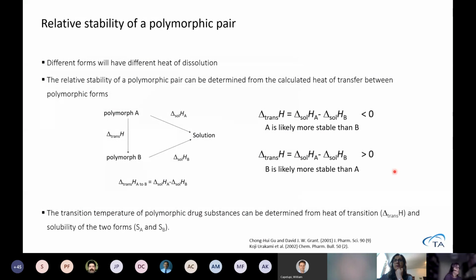So just start with the relative stability of a polymorphic pair. Different forms would have different heat of dissolution. So we can determine the relative stability of a polymorphic pair by calculating the heat of transfer between the different polymorphic forms. Well, you can do this with a DSC. You can get the transformation by increasing the temperature and get the transformation from one polymorph to another. We can also do it by dissolution calorimetry. As I say, we put it in an ampule, and we crush the ampule in a bulk liquid, and we measure the heat of dissolution.